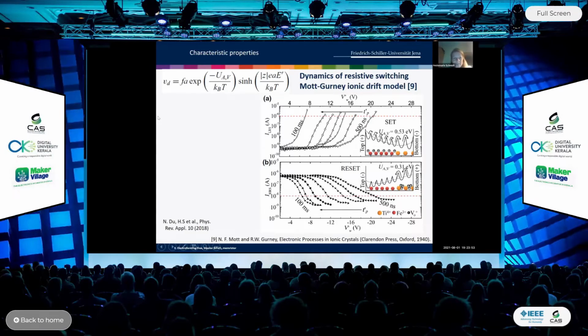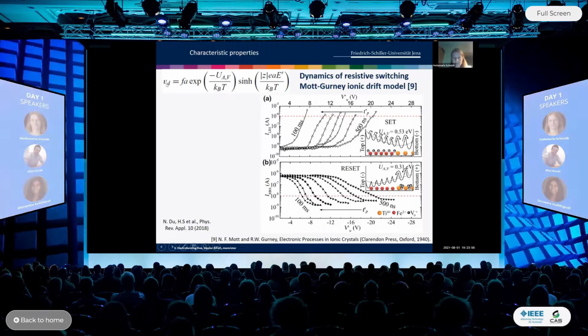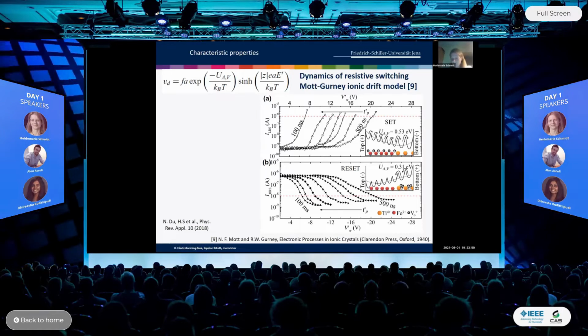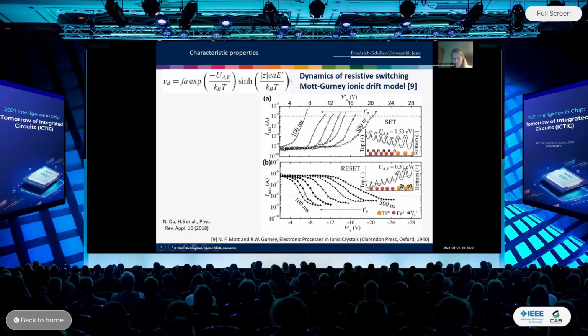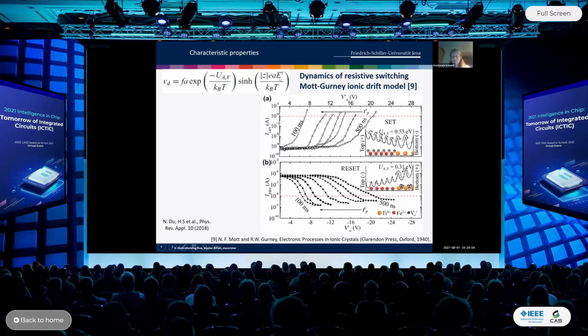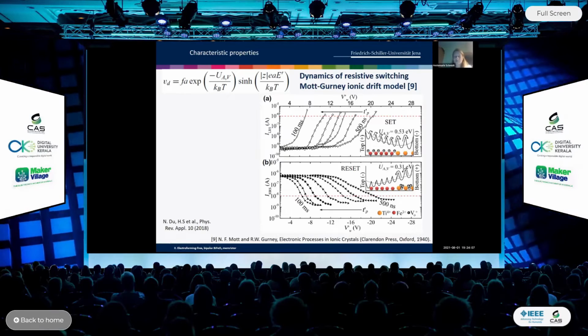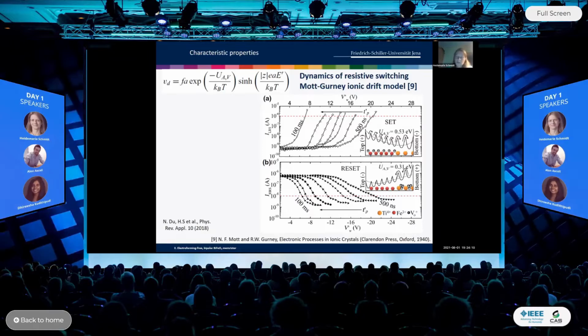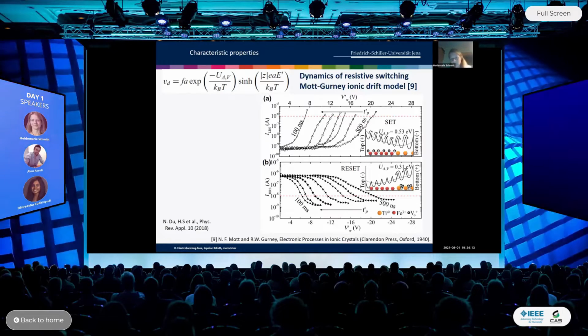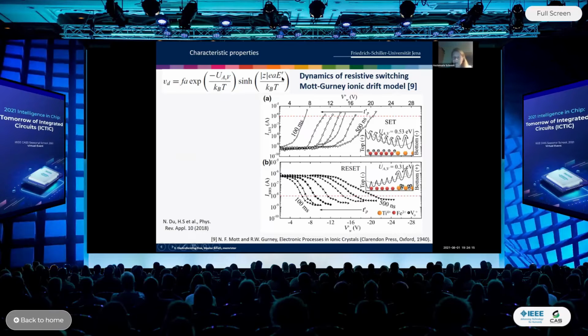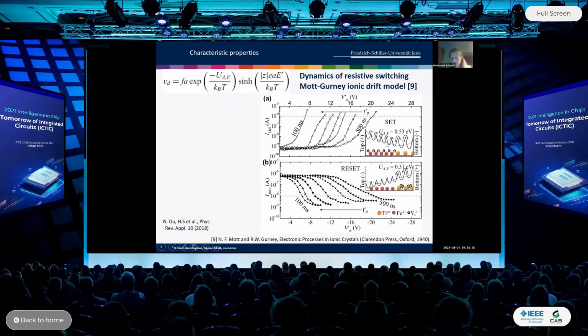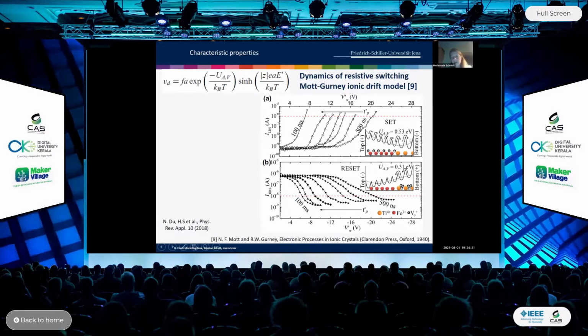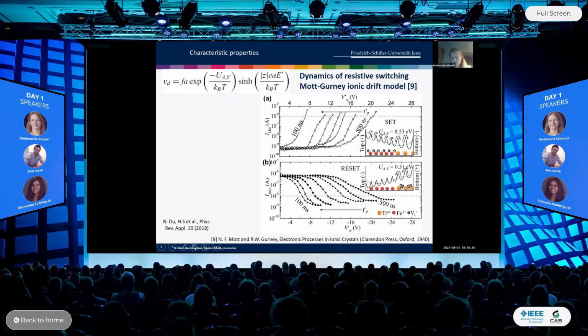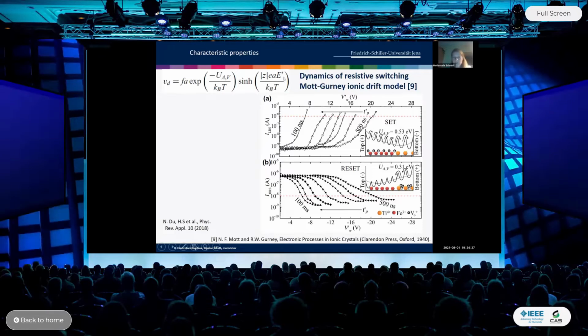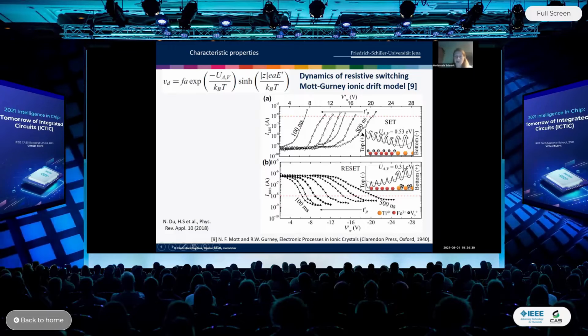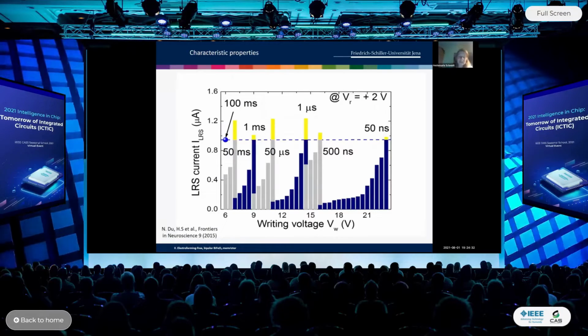And we have seen that indeed the drift velocity of oxygen vacancies scales exponentially with the electric field. This is very interesting because from free carriers, for example, holes and electrons in silicon, we know that there is a saturation drift velocity. That's not the case for ions, which are actually hopping over the potentials of the crystal field. The drift velocity of such ions depends exponentially on the applied electric field. But what does it mean for the application of such transistors?